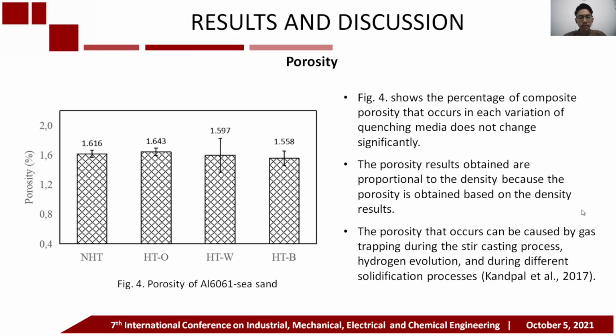And the next is porosity. Figure 4 shows the percentage of composite porosity that occurs in each variation of quenching media does not change significantly. The porosity results obtained are proportional to the density because the porosity is obtained based on the density result. The porosity that occurs can be caused by gas trapping during the stir casting process, hydrogen evolution, and during different solidification processes.